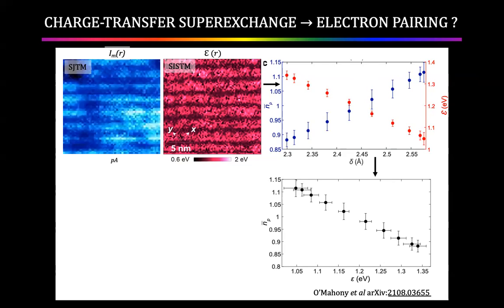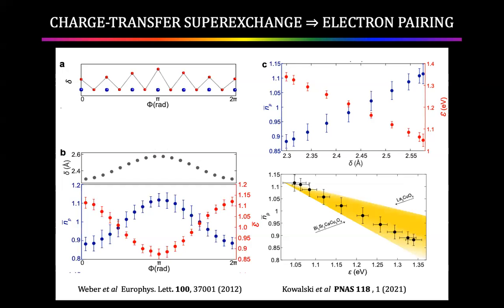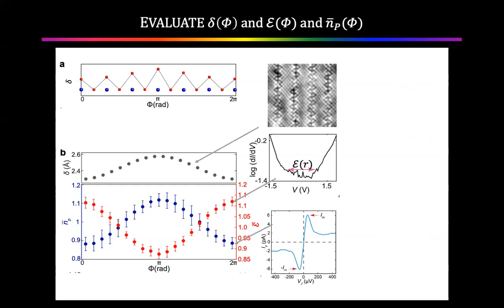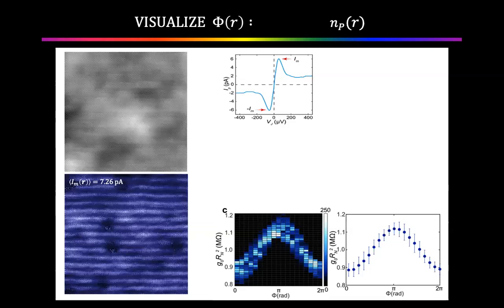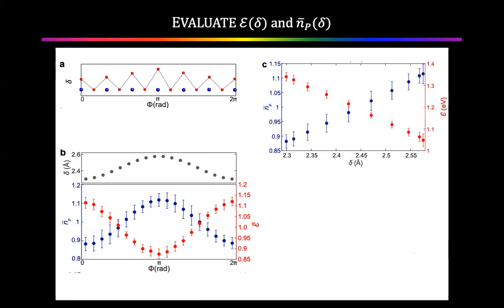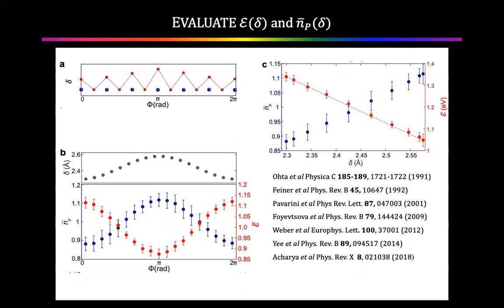Can you say again how you normalize the pair density from the... So in this case, there's a mean value of the Josephson current. So we normalize the experimental data by the mean value. We're just reporting departures of the density from the mean value of density, labeled 1. So there's about a 15% enhancement, and about a 15% suppression from the mean value. Now, the way we normalize it in the theory is to the parameters relevant to the material reported by the theory.